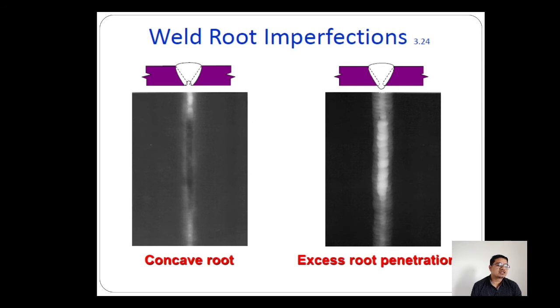And on the right side where excessive root penetration is shown, it appears lighter in radiography. So lighter means excessive root penetration, and why is it darker otherwise? Because thickness is becoming less. When thickness is less, it seems darker, and when thickness is higher, it seems lighter. So the lighter one is called excessive root penetration, and the darker one is called concave root.